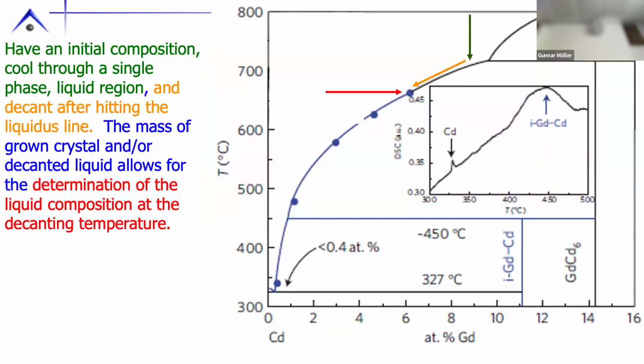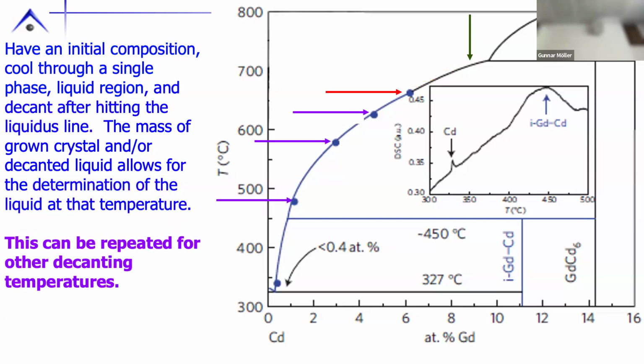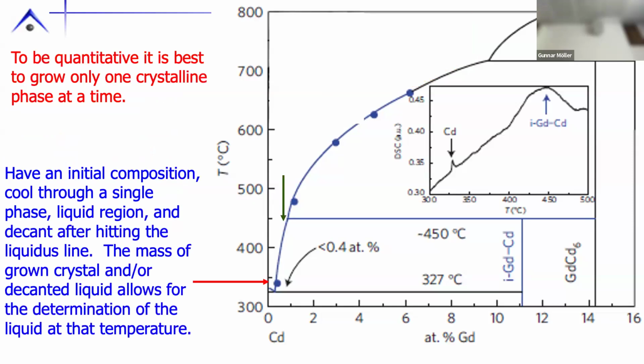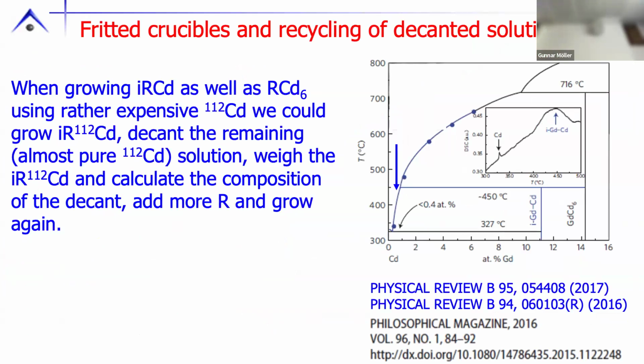So let's have a growth. I don't know where this liquidus line is. I don't know where I'm hitting, but if I hit and grow single phase GdCd6, when I decant, I can weigh how much GdCd6 I grew and subtract it from what I put in. That gives me this composition, pink. I can cool to lower temperatures and put other data points on. If I cross a peritectic and start growing another phase, it's more convenient to come in with a composition where I again grow a single phase. If I know this composition, I can put another data point on. So we can determine phase diagrams. We can correct phase diagrams. This is useful.